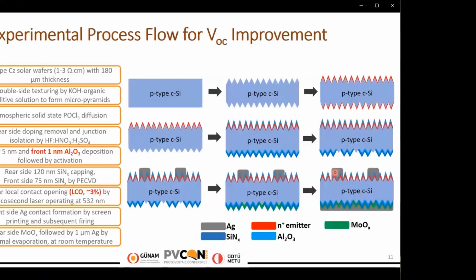In order to improve open circuit voltage of the PERC with molybdenum oxide solar cells, another cell was fabricated with additional passivation improvements. Starting wafers, texturing, diffusion, and single-side etching processes were kept the same as in previous studies, while 1 nanometer aluminum oxide is added under the front anti-reflective coating for better chemical passivation on the front side. The local contact opening was reduced to 3% from 7% in order to compare the results with the optimized homogeneous emitter PERC structure we fabricated by industrial tools.